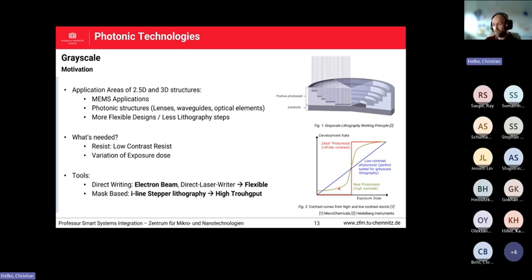In green is the real photoresist, meaning you have a high contrast resist, where the dose is becoming higher, the resist is exposed, and then at a certain exposure dose, all the resist is exposed. So we have not a 90-degree edge, but a small slope. And for grayscale lithography, you need the blue one here, which is a low contrast photoresist. This means at every point of a certain dose, the photoresist will expose to a certain, let's say, thickness or layer of the photoresist itself. And this is also seen here, meaning these arrows here, this is small dose, higher dose, and the highest dose here will expose the whole photoresist away. So this is the other point which is needed. You need a low contrast resist, and you need the variation of the exposure dose, for example, as is shown here in these arrows.